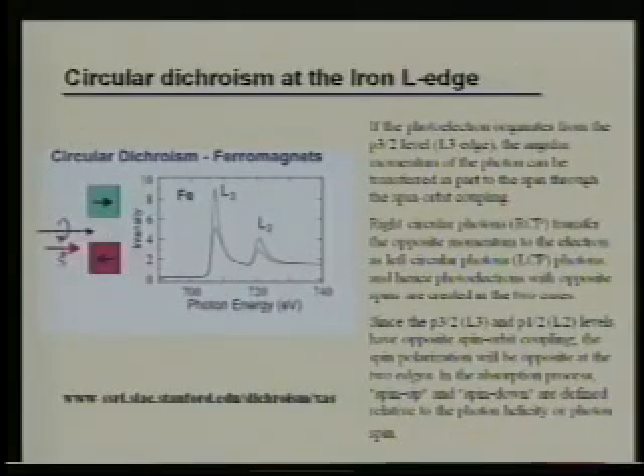So if we look at something like an iron edge, and if we take it in one spin direction or another spin direction, you can see that the L3 and L2 edge are changing. And from these changes, you can actually get information about the magnetic moment in these materials. There are other techniques for extracting magnetic moments from materials, but the useful thing here is, again, it's element specific.